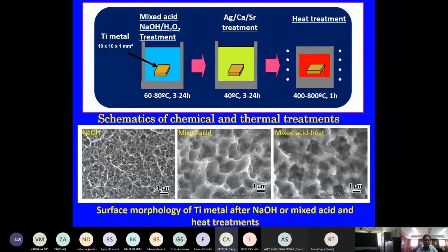If you treat with sodium hydroxide and look under SEM at the surface morphology, because of the chemical reaction between the titanium and sodium hydroxide or hydrogen peroxide, it forms a hydrogen titanate or sodium titanate layer over the surface. It is basically a 1 micron porous layer, and it forms over the entire surface of your 3D printed implant or any kind of metallic implant.